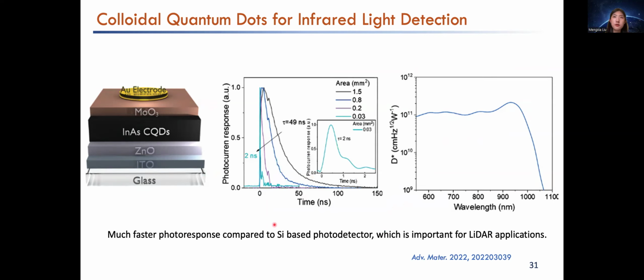One successful result is to apply it onto an indium arsenide quantum dot for photodetection in the near infrared. This generates a good photodetection range from visible all the way up to 1050 nanometers, which is similar to the response range of silicon, but it has a much better detectivity compared to silicon and also a much better photocurrent response time, as short as 2 nanoseconds, which is very important for LiDAR applications.